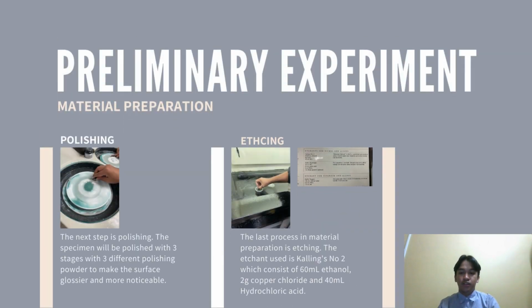The next process of material preparation is polishing. The specimen will be polished in 3 stages with 3 different polishing powders to make sure the surface is glossier and more noticeable. The last process of material preparation is etching. The etchant used is Kalling's number 2, which consists of 60 ml of ethanol, 2 grams of copper chloride, and 40 ml of hydrochloric acid.